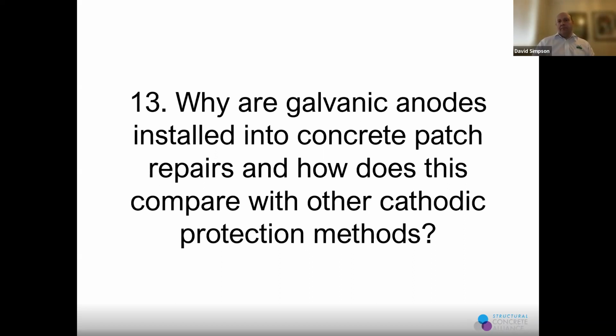patch repair scenario, really. Highways England now have included this as a standard spec. It's included within the ISO standard in the notes in terms of cathodic prevention. And typically, as we've said, with new construction, which is cathodic prevention, and patch repair, the current densities are a lot lower. The amount of current we have to pass on to the steel is far lower with prevention, which again lends itself to galvanics. And that's typically why I think they're used more often than not now.